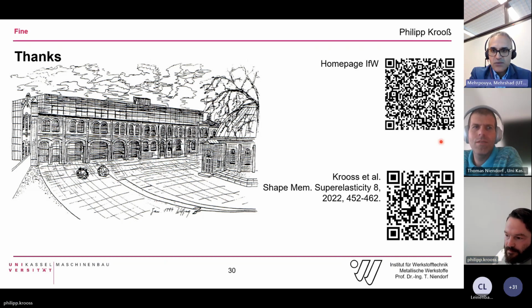Okay, thank you. There is one question here, and thank you for your wonderful presentation. Could you please explain the mechanism of formation of Ni4Ti3 precipitate? How was this confirmed? Okay, it was confirmed by diffraction in the TEM. So we cut a small lamella via focused ion beam from the sample, and then we moved to the TEM, transmission electron microscopy, and then we did some diffraction on certain areas, on certain orientations.